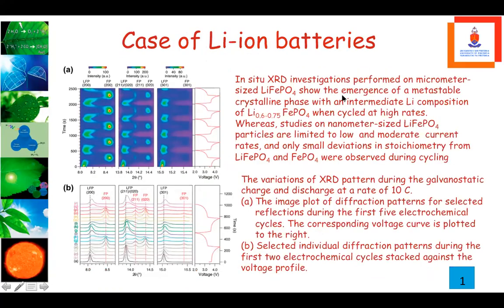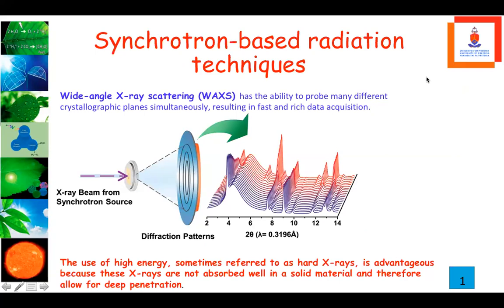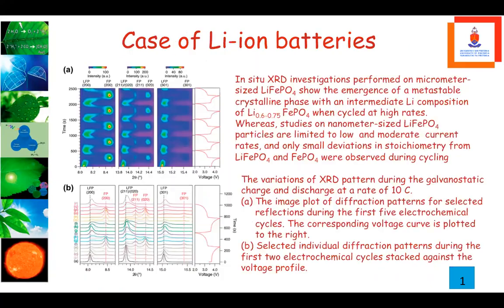We have a case of lithium ion batteries, which I think people will be interested in because batteries are a storage. In situ XRD investigations performed on micrometer size lithium iron phosphate show the emergence of a metastable crystalline phase with an intermediate lithium composition of 0.6 to 0.75 when cycled at high rates.